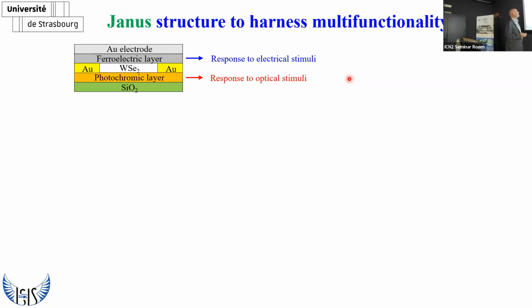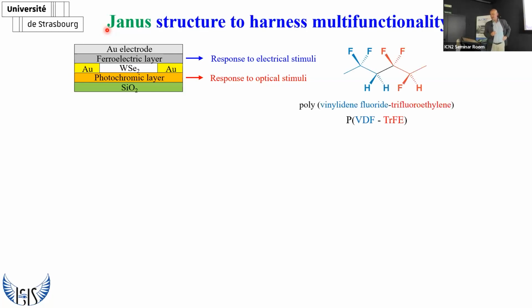What I showed you so far used a photochromic layer, which we have now decided to put underneath the 2D material, because this can be more easily addressed from far away if we have light going through all this stack of stuff in between, which I will tell you about in a second. And so we can change the state of the photochromic layer. So we put this underneath the tungsten diselenide, whereas on top of the tungsten diselenide, we decided to play with a ferroelectric layer.